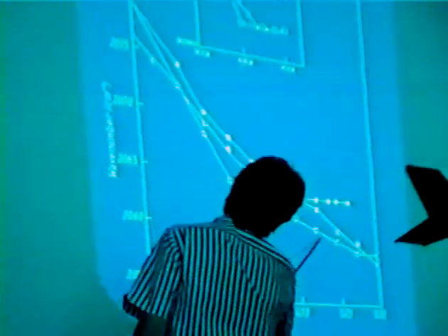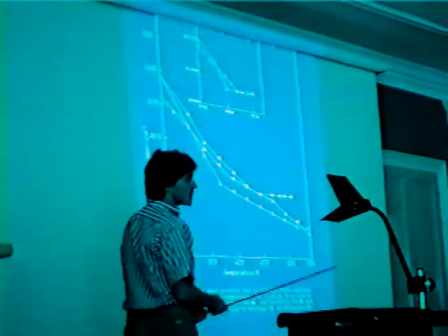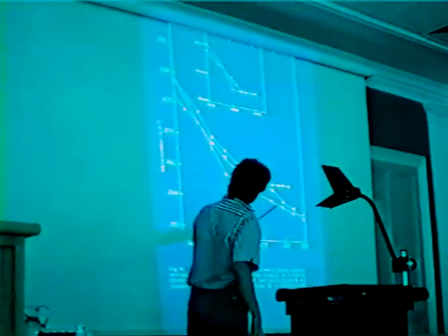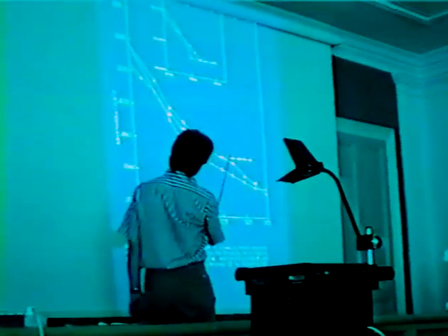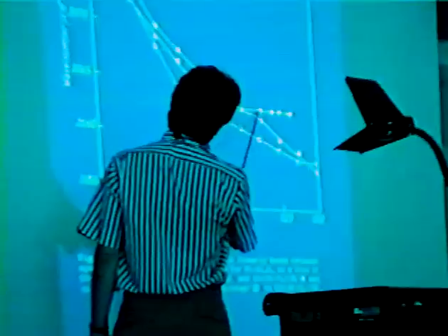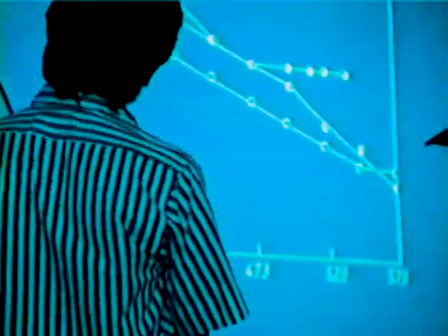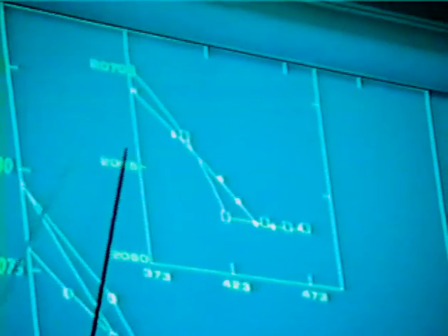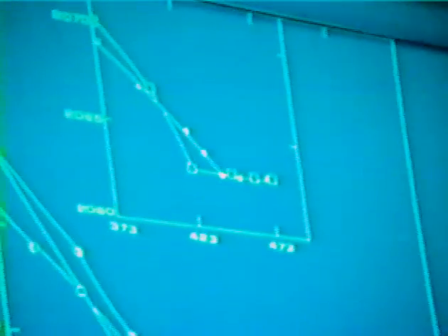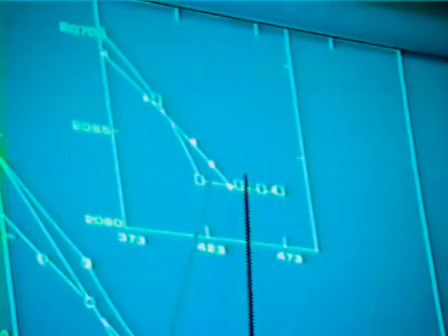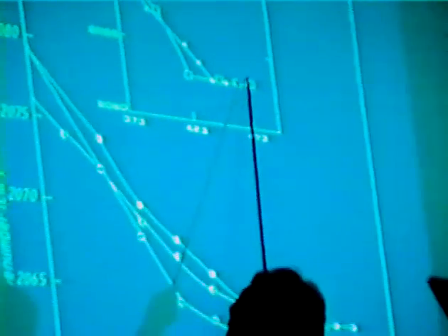So if we just ignore, first of all, the two lower curves here, as I said earlier, we only see invariance where there is an excess of oxygen in the flow. So these are for stoichiometry and in a CO excess. But again, in the case of platinum, this is 1% CO, 1% oxygen, we see a short period of invariance in the carbonyl stretching frequency, about 2063 wave numbers. And when you compare this with the behaviour of the platinum-rhodium catalyst produced by the two impregnation sequences, in both cases we also see the short period of invariance.